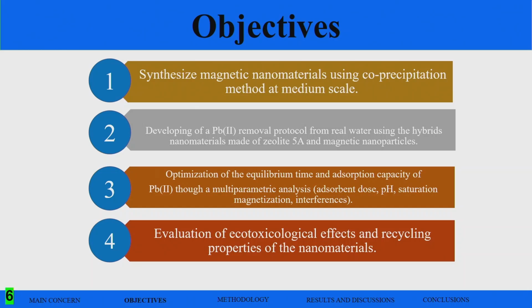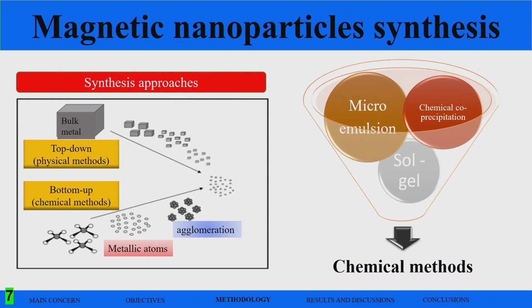So here, after the problem was mentioned, we have to synthesize the magnetite nanoparticles using the co-precipitation method at medium scale. I will say briefly why we need to use the co-precipitation method and not other ones. Then the development of a lead removal protocol from real water using hybrid nanomaterials made of zeolite 5A and magnetic nanoparticles, some optimization of multiparametric adsorption parameters, and the evaluation of the ecotoxicological effects and recycling properties of the nanomaterials. As you all know, we have a lot of physical and chemical methods, top-down and bottom-up approaches, that we can use to produce nanoparticles.